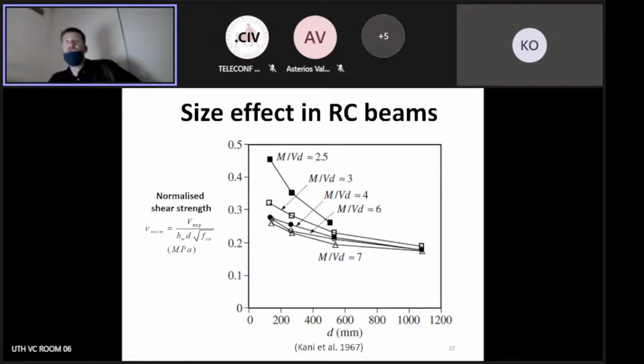And actually, there was one shear failure of a warehouse. I don't remember when exactly that was, but it was related to size effect. And since then, we started looking into this in more detail. So, as I said, FRP reinforced structures are more brittle, with wider cracks, more brittle behavior, larger deformations, and a larger level of damage. So we can really expect that this will be much more significant in terms of FRPs.